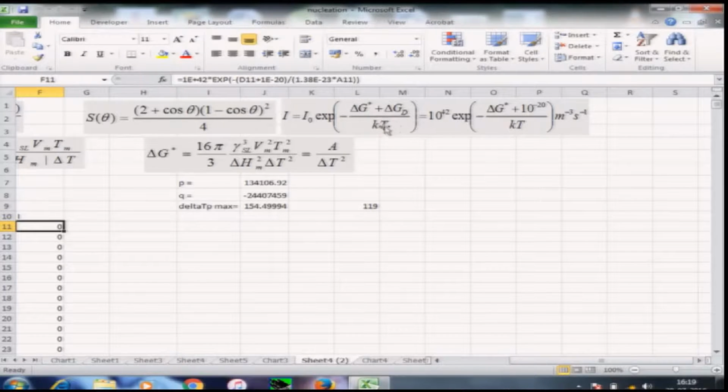But at the same time, temperature is going down, and if the temperature goes down too much, then a critical nuclei, for it to become supercritical, an atom has to jump across the liquid solid interface. The jump frequency of that will go down as the temperature goes down, simply because the atoms do not have enough energy at very low temperatures for them to jump.